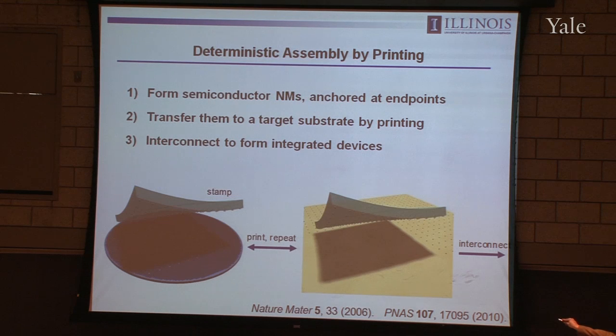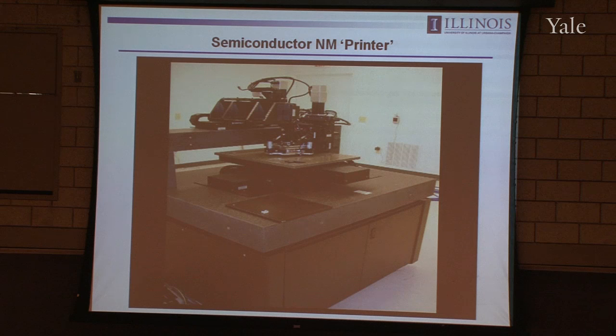So it all has to do with how you modulate the adhesion strength from a high adhesion value to a low adhesion value in a reversible and controllable way. And it turns out there are a variety of biologically inspired routes to doing that, using inspiration from gecko feet. You can exploit the viscoelastic nature of the elastomer to accomplish that kind of switching. And I won't get into those details. We just mention that that becomes the focus of the science in making this engineering approach work, is really understanding the physics of soft adhesion so that you can manipulate the adhesion strength on and off to facilitate that process. So you can build a tool around that kind of concept.